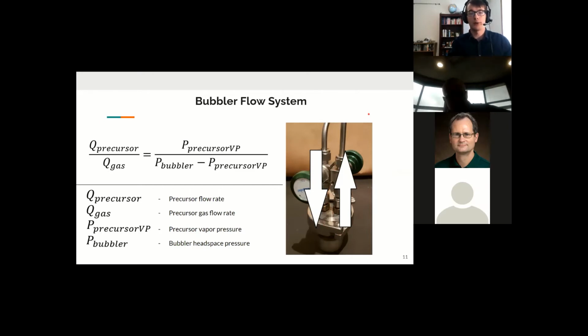The bubbler was cooled in an ice bath down to near 0 degrees Celsius during runs to further reduce the vapor pressure of TMS, allowing for more control of the precursor flow rate. The flow rate of the precursor in a bubbler follows this equation, where Q precursor is the precursor flow, so just the atoms of TMS flowing, and that's measured in sccm, so that's standard cubic centimeters per minute. Q gas is the flow of the precursor gas itself, that's flowing into the bubbler. P precursor VP is the vapor pressure of the precursor. We measured it in torr, and P bubbler is the pressure of the headspace of the bubbler.